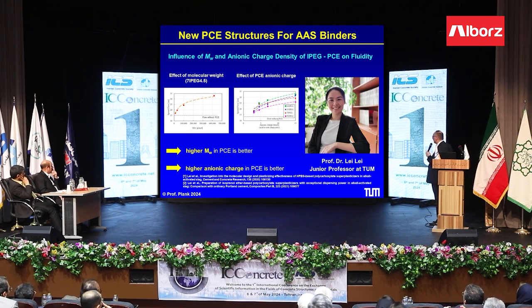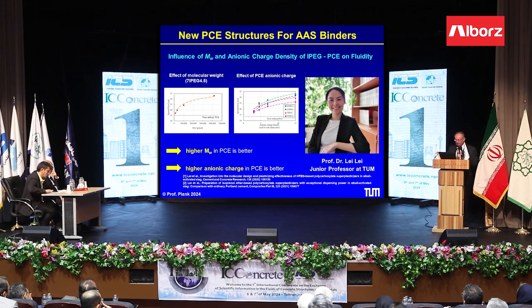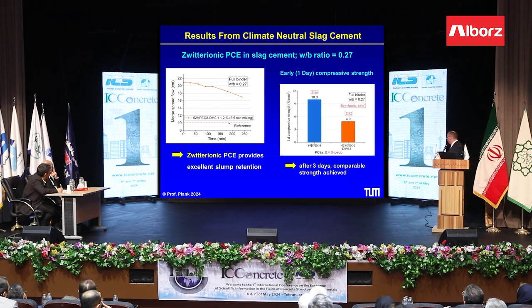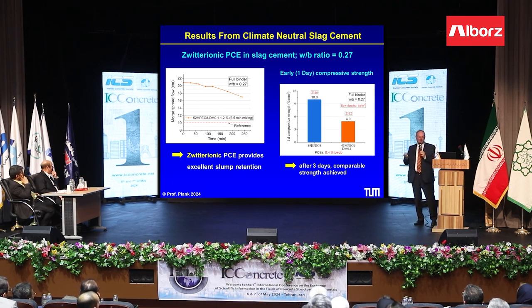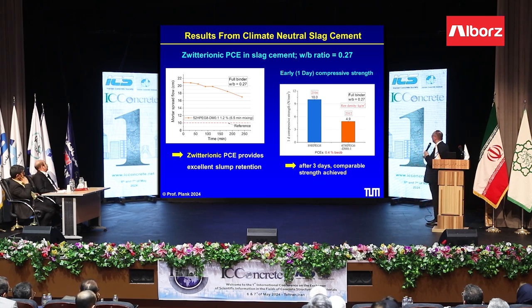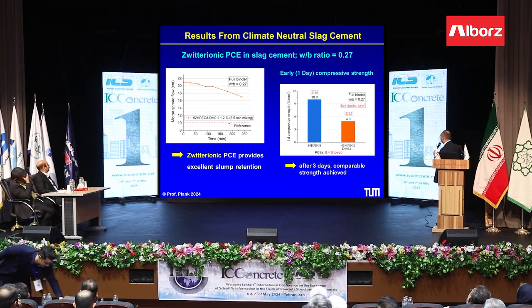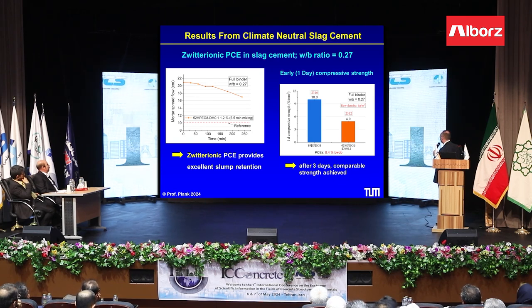And she found that you need a higher molecular weight and also a higher anionic charge, and then you have excellent superplasticizers even for those systems. Another solution for these slag cements are so-called zwitterionic PCEs, where we incorporate a cationic monomer also into the PCE. And as you can see here, in a slag cement, they give very good fluidity and also very long slump retention, 3-4 hours. So they work very well. The only slight disadvantage, which they have when the dosage is high, is that they reduce the very early strength. This is the one-day strength, but after 3 days, there is no such effect anymore.